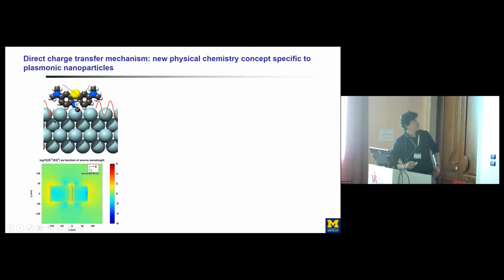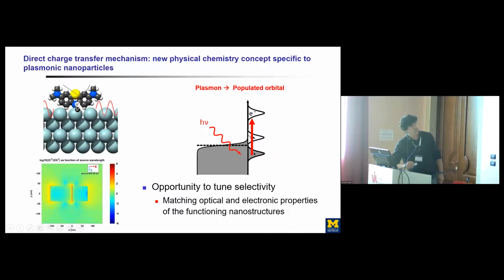The one mechanism that we thought might play a role in this process is the direct charge transfer mechanism. And the idea here is that rather than exciting electrons in the bulk of this metal, because of this resonant interaction and because you're concentrating the energy of light close to the surface, very much at that interface between the molecule that's adsorbed and the nanoparticle surface itself, it would be possible to have direct excitation of electrons, or this optical excitation, at this interface of the molecule and the surface of the nanoparticle.